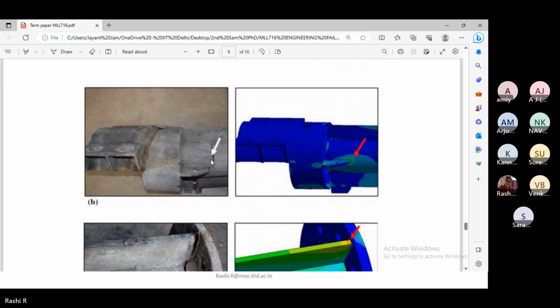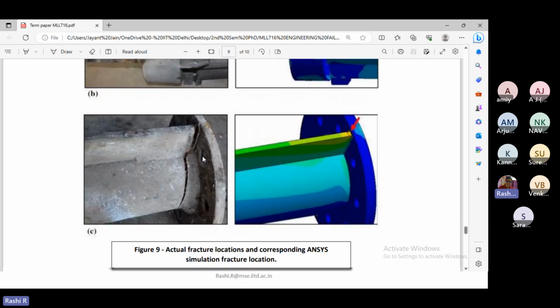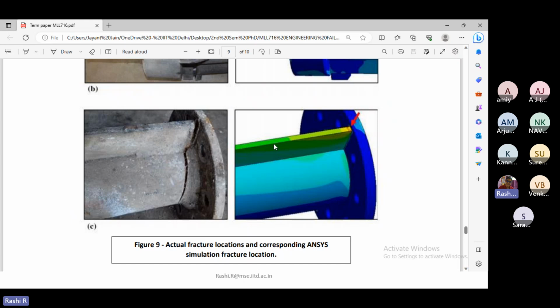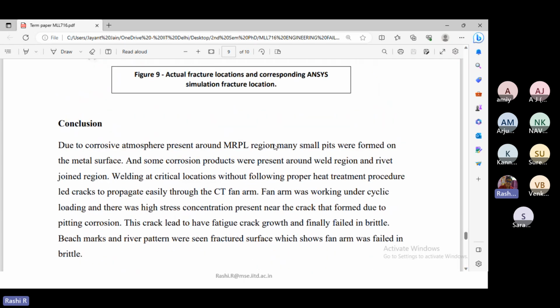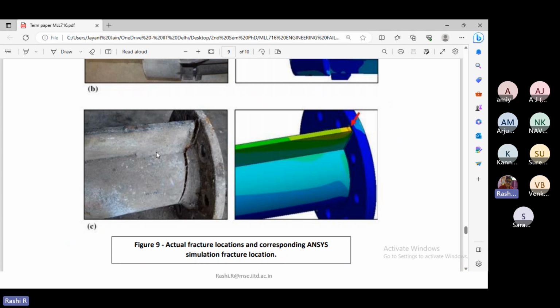And then because of the welding and weld joint, the stresses were present, as there was also a weld joint at 90 degrees. The stress concentration was also higher in that region, and you can see one crack corresponding to that. And similarly, another crack corresponding to this. So in order to avoid this, once the welding was done, you have to do the proper heat treatment. And once the heat treatment was given properly, avoid keeping it at 90 degrees so that the stress concentration region will not be high.